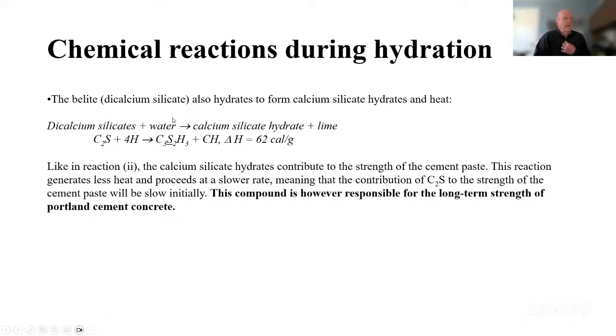Okay, so this is this calcium silicate, which gets hydrated, and you can see that it will form more calcium silicate hydrate and more lime. Okay, more calcium oxide. And remember what we talked about earlier, that when you form this lime, if you mix it with more water, you get calcium hydroxide. If you expose that calcium hydroxide to CO2, it will absorb and react with CO2 to form calcium carbonate again at lower temperatures.